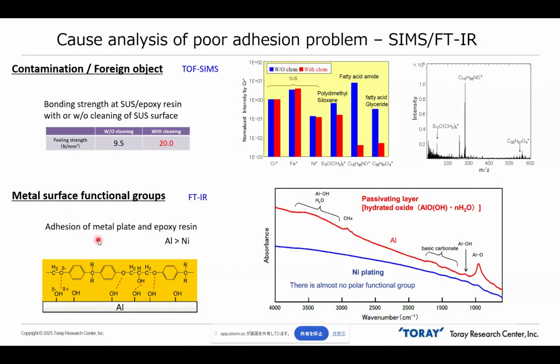In the lower part, we would like to consider the adhesion strength between a metal plate and epoxy resin. In this case, the adhesion strength of aluminum is better than that of nickel. Then we examined the surface of the metal plate by using FTIR measurement. In the case of aluminum, we could detect an OH group at the surface. But there is no significant functional group at the surface of the nickel. The OH group at the surface of the aluminum can make hydrogen bonding with epoxy resin. So the adhesion strength between aluminum and epoxy resin should be greater than in the case of nickel. So we use many kinds of analytical techniques to evaluate electronic packaging.